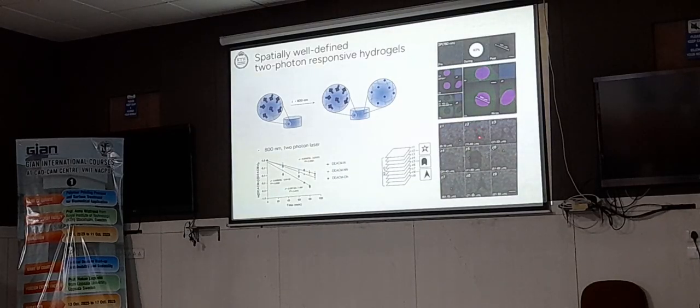And then between 41 and 50 micron, we made another figure, and at 71 to 80 micrometer down, we irradiated again. And in between those, you can see that it's not irradiated. The fluorescence is the same. But where we have irradiated, we can see that fluorescence is gone. So not only on the surface, you can also go down and irradiate specific spots and make the hydrogel active where we have irradiated.